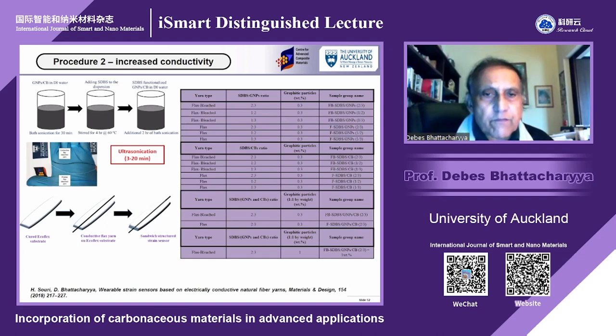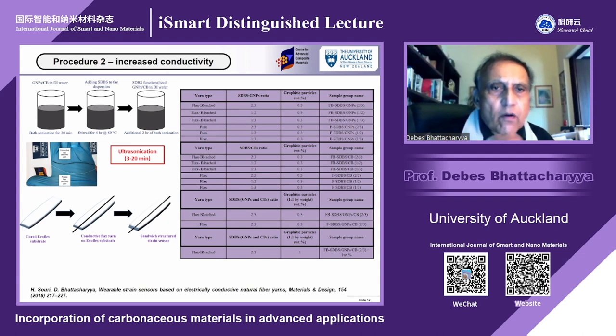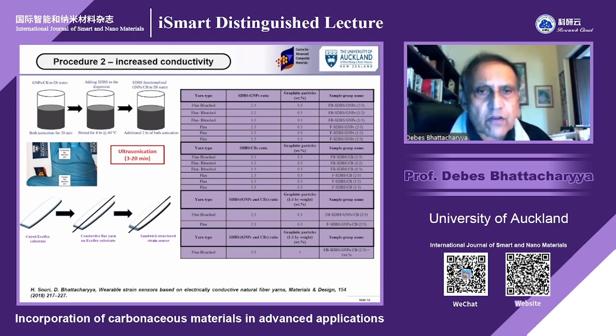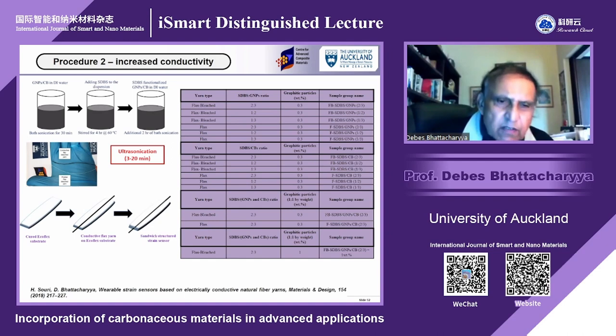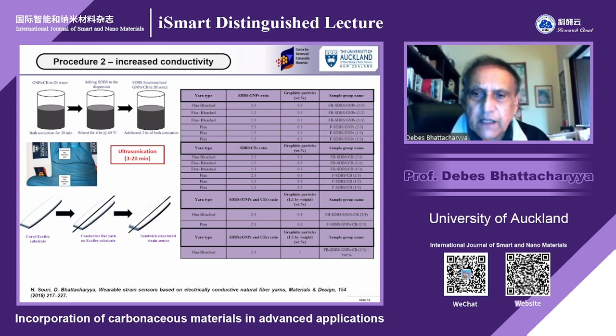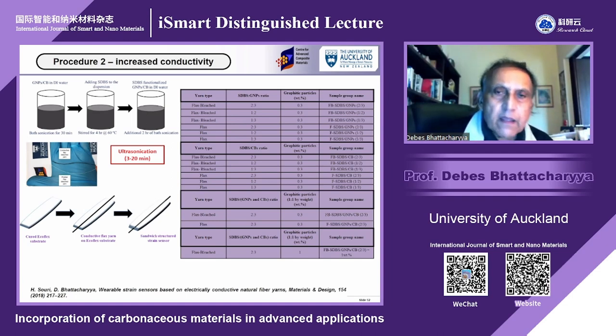In procedure two, we went from just one fabric. With that one fabric, we tried to have conducting flax yarn, and also did ultrasonication from 3 to 20 minutes, with slight variation of the properties, and also conducted a Taguchi type analysis. It was published in Materials and Design in 2018. So we tried to see how the material can improve.